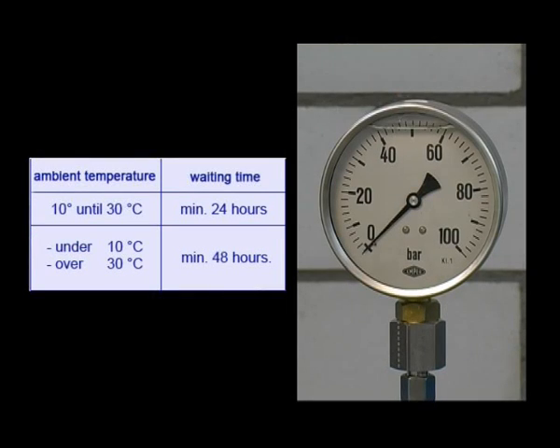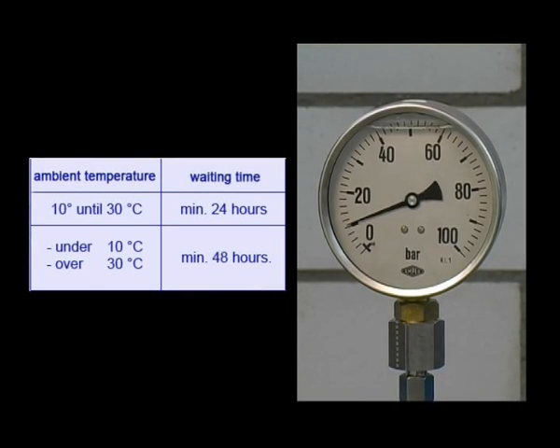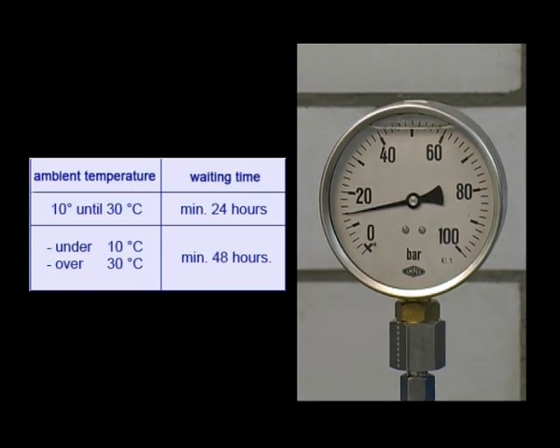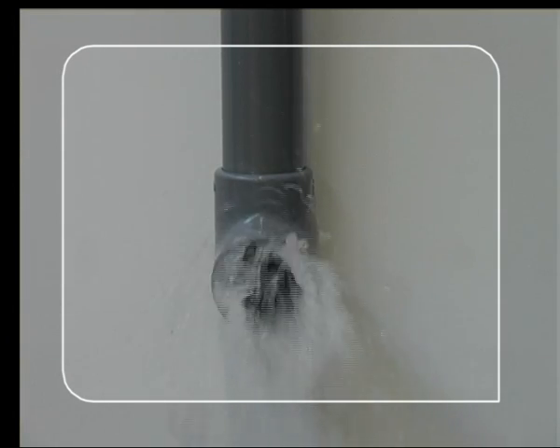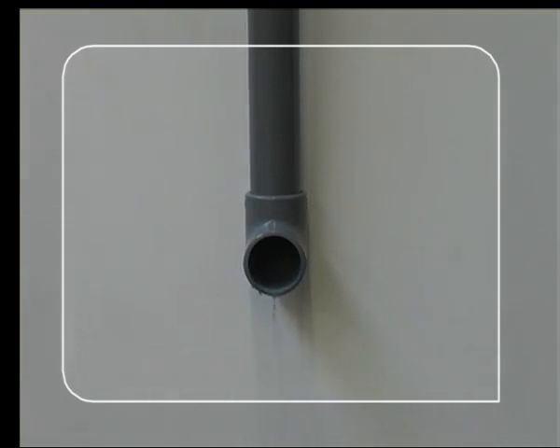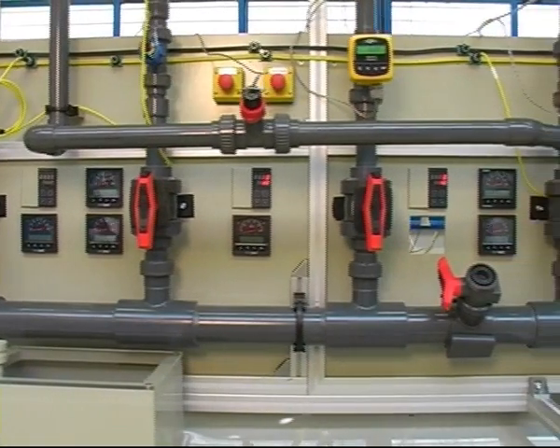As a guideline for practical on-site operation, allow a waiting time of at least 24 hours for drying at temperatures between plus 10 degrees Celsius and plus 30 degrees, and allow at least 48 hours at temperatures below plus 10 degrees and above plus 30 degrees until an internal water pressure test can be carried out. Subsequently, the pipeline must be thoroughly rinsed or purged to remove any solvent vapors. After the leak test, it's advisable to keep the system filled with water until commencing operation, unless there's a danger of frost. Adhesive joints made in this way are durable, leak-proof, and ensure safe and lasting system operation.